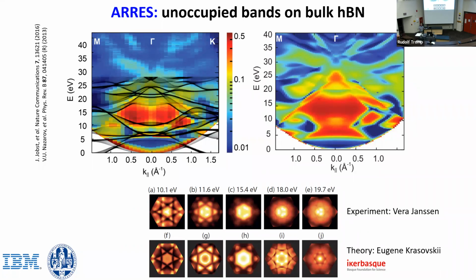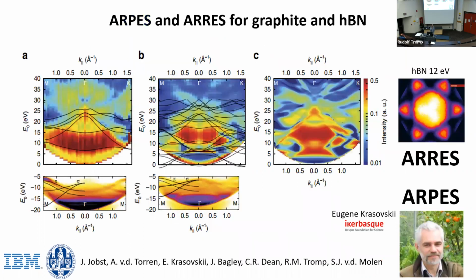So you see here at 10 eV, if you look at the band structure as a function of the in-plane momentum, it's very highly non-uniform, right? And it's got the 6-fold symmetry. You see here, it gets to a 3-fold symmetry, etc. And here are simulations that show similar effects. Here is graphite, hexagonal boron nitride.